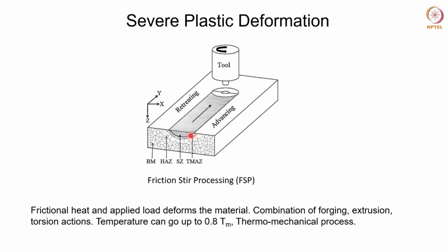And then next to it, like in any other welding process, in friction stir welding or friction stir processing also, you have the heat affected zone, which is the region that is subjected to a heat cycle but not any deformation, right? So this region will display a coarser grain size compared to the other two regions, right? So these are the different techniques by which grain refinement can be carried out in solid state. And many of these, in fact, have become very popular for grain refinement of aluminium alloys.